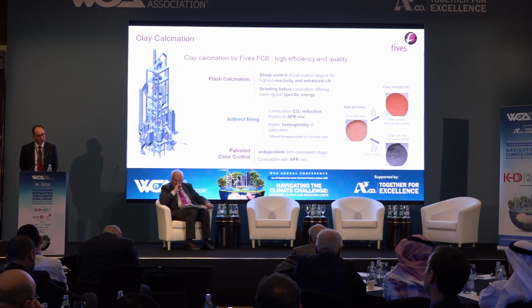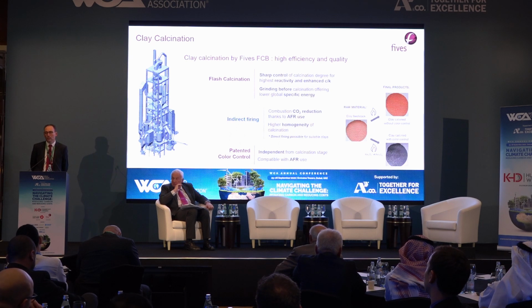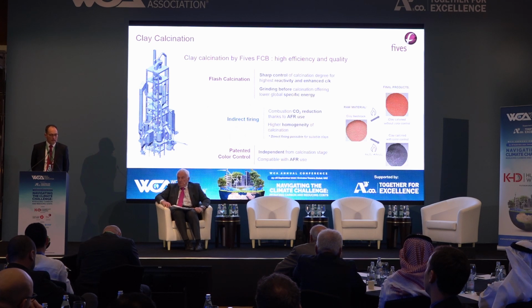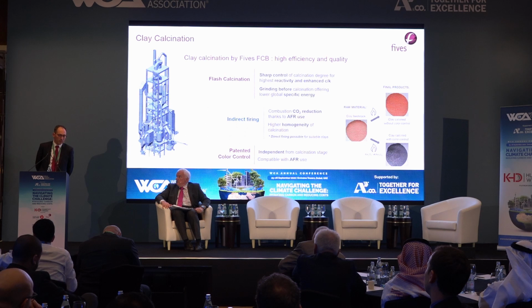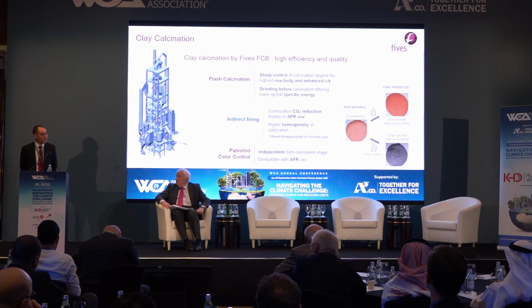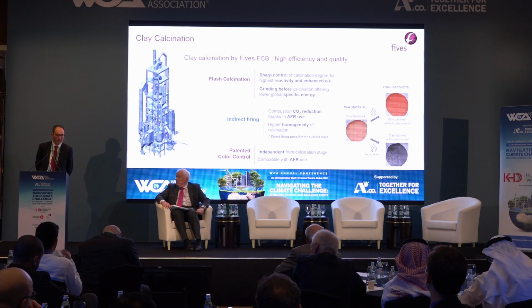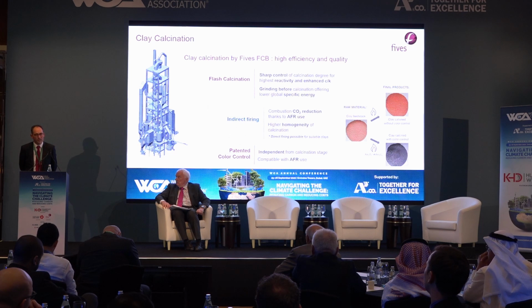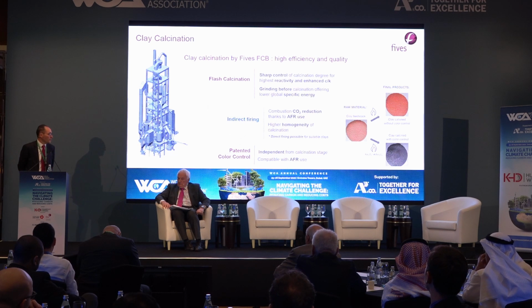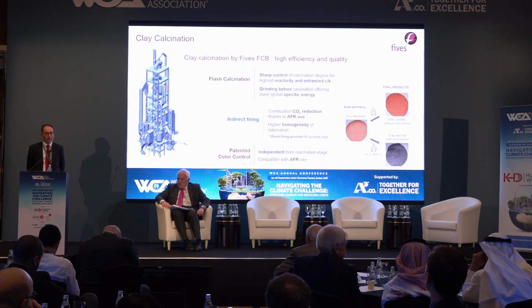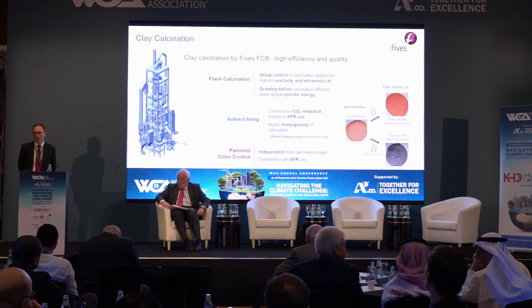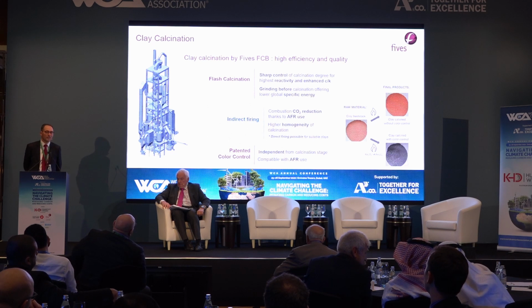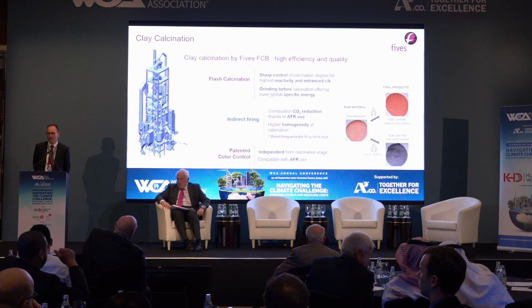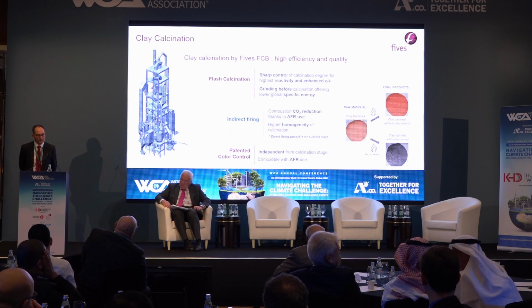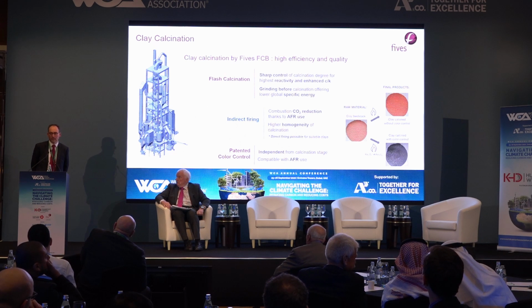And it gives a higher homogeneity instead of the direct contact with the flame. And also, and I was joking a little bit about the color, for sure when you calcine clay, because of the iron content, you obtain this reddish color. And the market seems not to be ready to sell reddish or pink cement. So we have developed the appropriate process to keep the color under control and have a gray product that will match the habits of the cement industry to deal with the gray product. And this is much more easy with the flash calcination than in a rotary kiln.